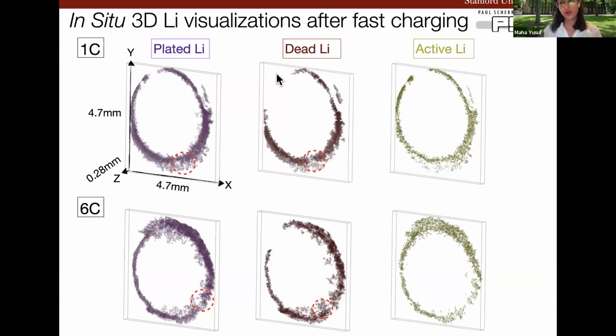Dead lithium is the one that is irreversibly plated, which means this is the main culprit. There is no way this can go back to the cathode during battery discharging. And active lithium is the one that is still active and is electronically connected to graphite. So distinguishing between what parts of the battery form active versus dead lithium is extremely important to understanding battery degradation, so that we can understand spatially how to engineer the battery in such a way that we can minimize dead lithium.